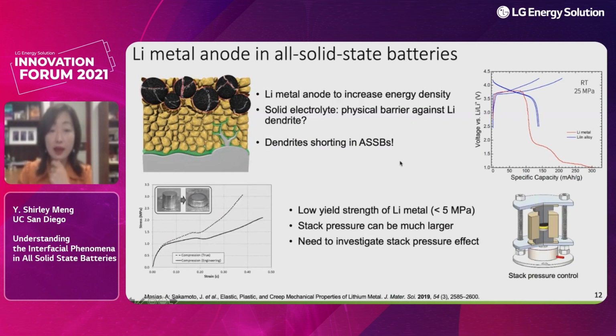So let's look at some of the interesting properties of lithium metal, because earlier work done by Professor Sakamoto's group focused on the fundamental mechanical properties of lithium metal. That taught us that when we design solid state batteries with lithium metal, going for very high stack pressure may not be the most effective method, because lithium has very low yield strength—less than 5 megapascal. So think about what happens when we put very high stack pressure, since in solid state batteries we typically apply tens of megapascal of stack pressure.